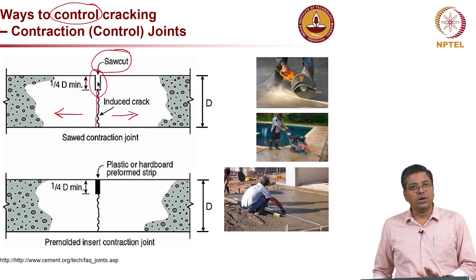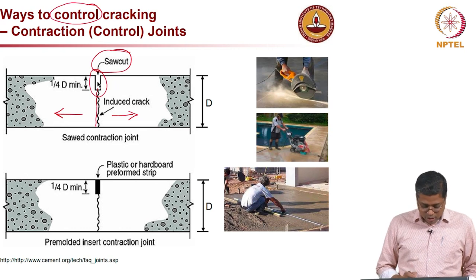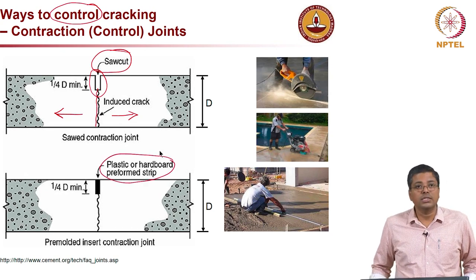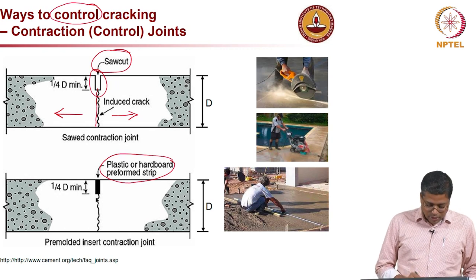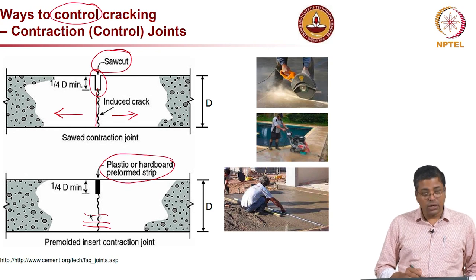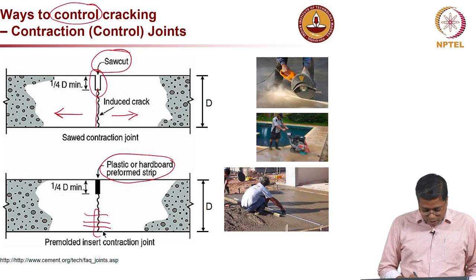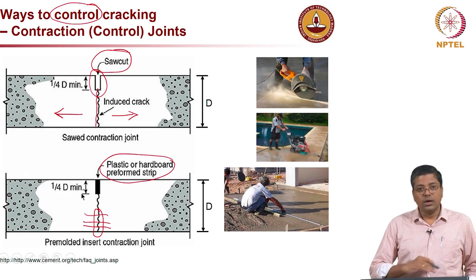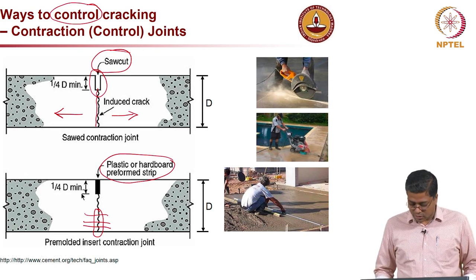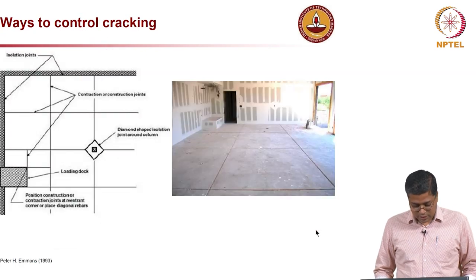So essentially we are controlling the location, or defining the crack location, by doing this saw cutting. And to prevent other issues, we should also ensure that the saw cut region is protected, because otherwise if there is a crack and you have rebars going like this, it will corrode right here. So you have to protect this saw cut or joint from moisture. Providing a good sealant is always a good idea in such cases.